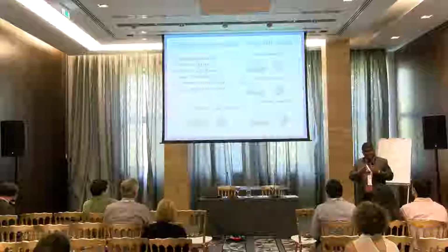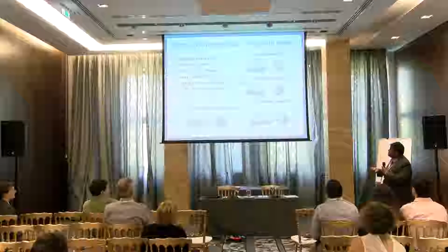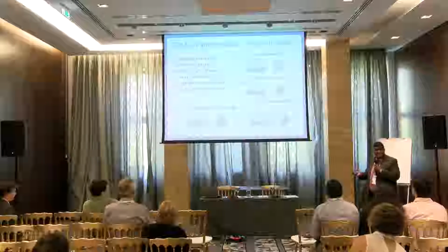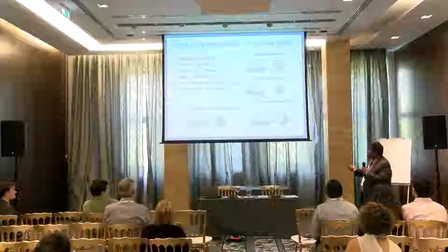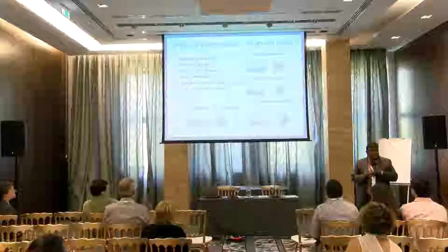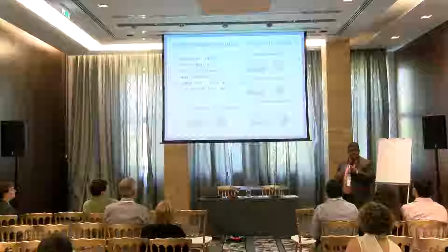That affects the damage mechanism on the fabric, and as a result, the energy dissipation and absorption is significantly affected by the type of projectile. So we have covered these 4 common projectiles with the data given. We considered a velocity range of 30 to 130, which is considered a low speed range in ballistic impact. It could be a small projectile. We determined the friction coefficient between such fibers experimentally, and it complied with literature data at about 0.22, and we kept the projectile mass the same, for consistency, at 7.5 gram, which is a small projectile.